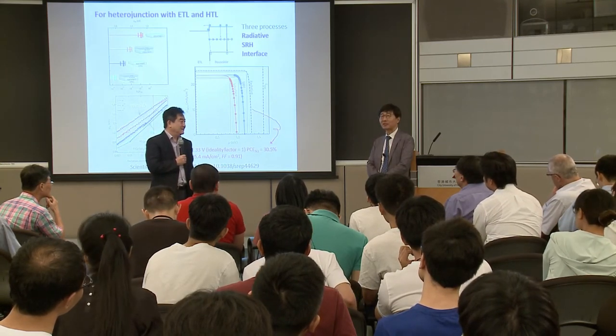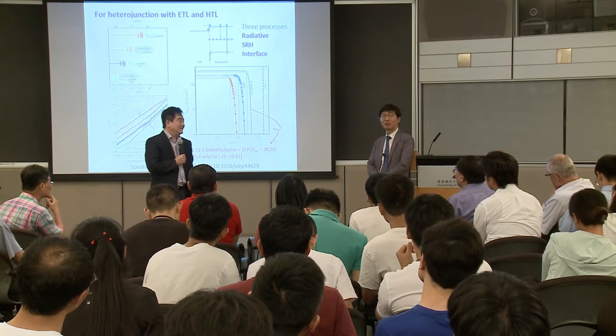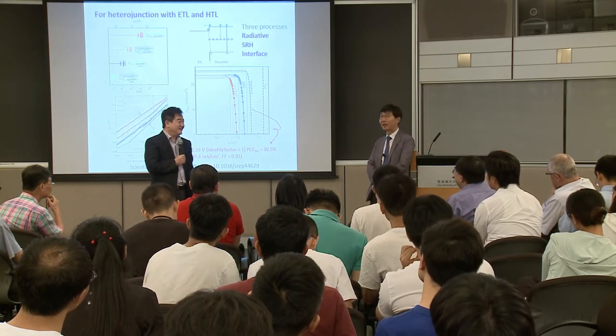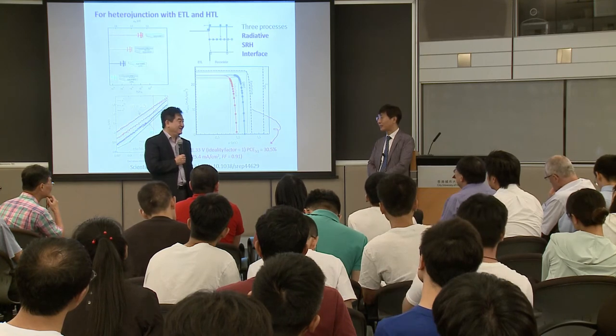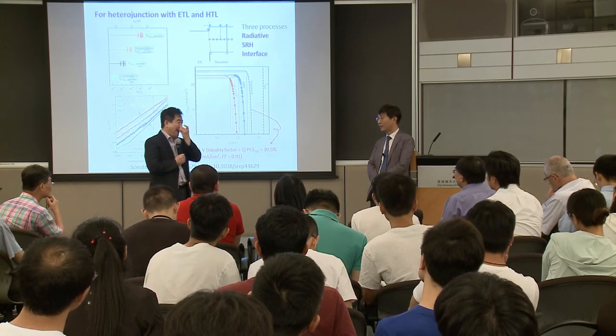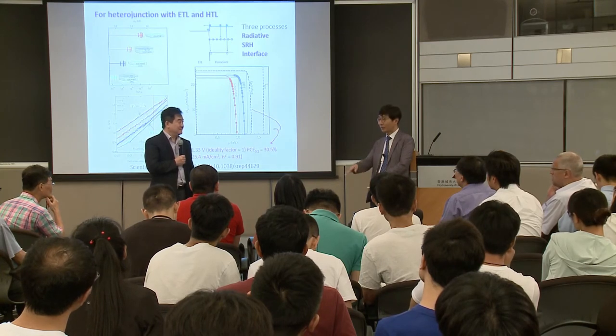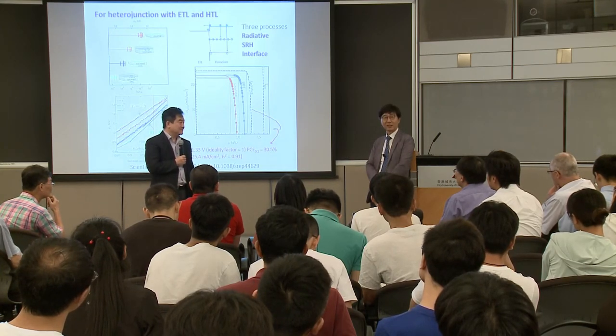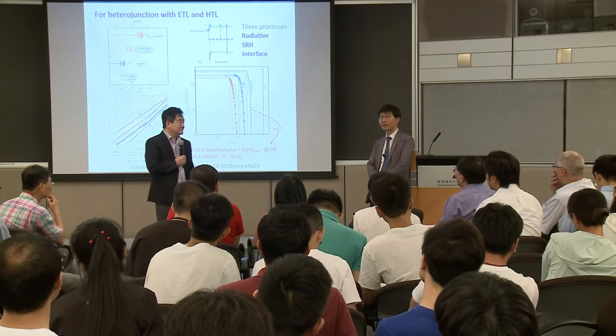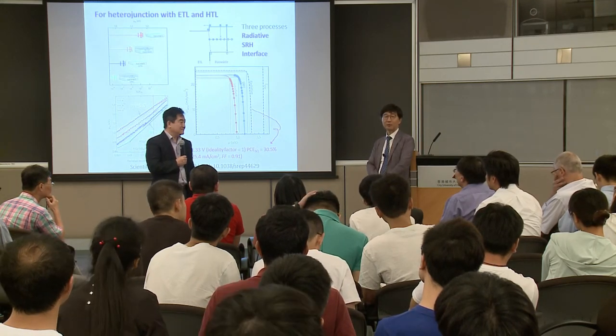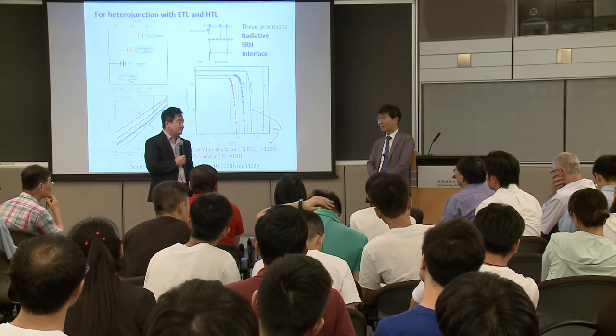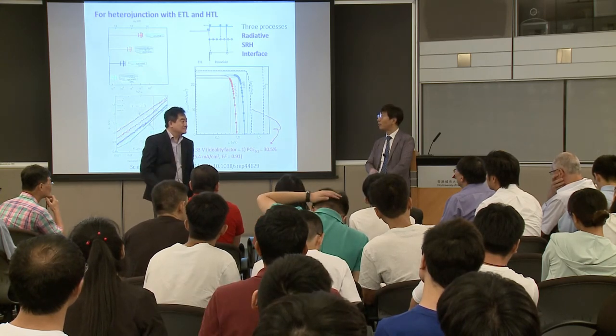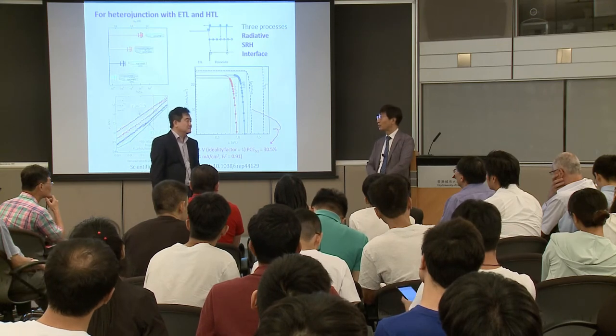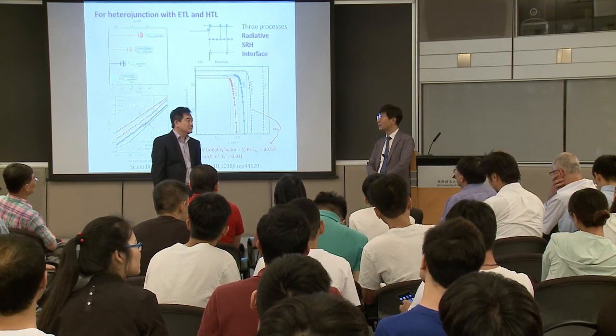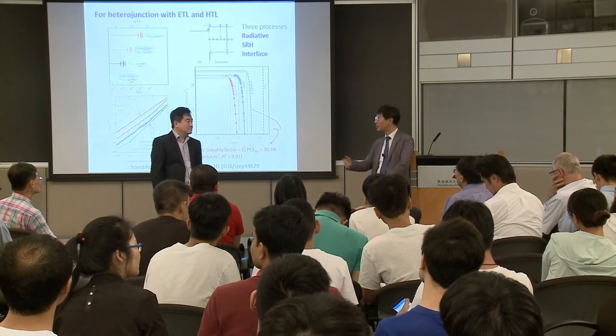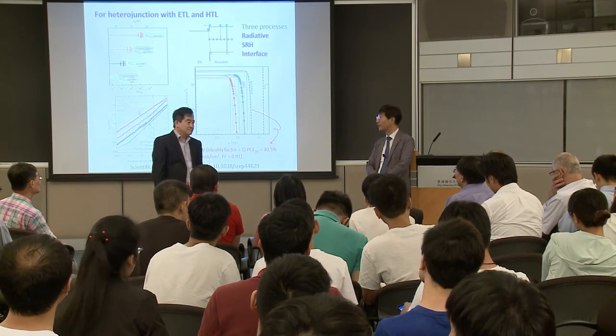So our best efficiency is around 20%. So it's not 22% efficiency. I asked my student why you cannot get the 22% efficiency. Look carefully at the report and just mimic the recipe. Even so, they reported to me that they could not get even close, and it was worse than our method. So it's very difficult to achieve such a high efficiency. But because this efficiency is certified, we have to believe it anyway.